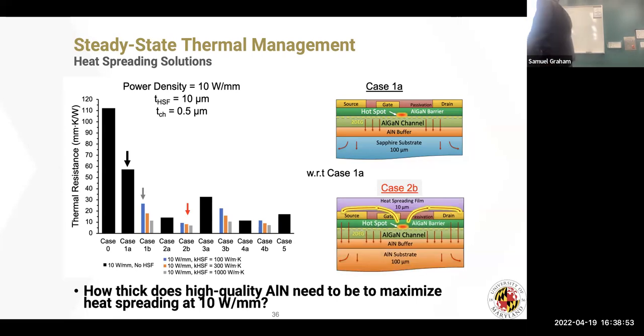Now, what happens if I change this to having an aluminum nitride substrate, so high thermal conductivity, you can see that now it drops further down. So the actual case of what we're making now is this case, because it's the easiest one. We start out with commercial aluminum nitride substrates. We can actually play around with this aluminum nitride layer here, make it thicker to help with heat spreading, and then we put a heat spreading film on top, and I'll show you a little bit about that.